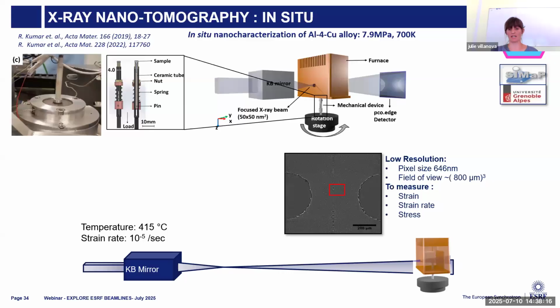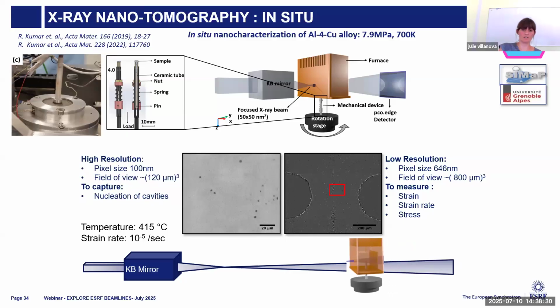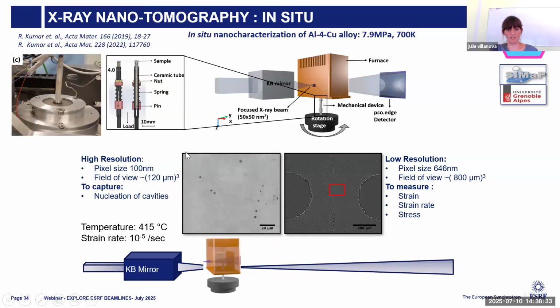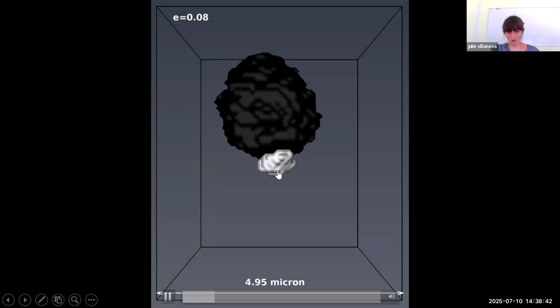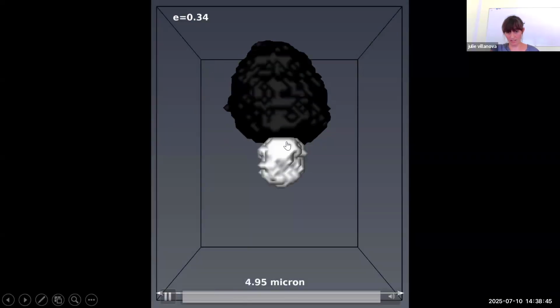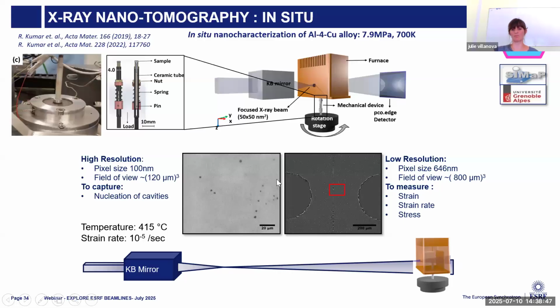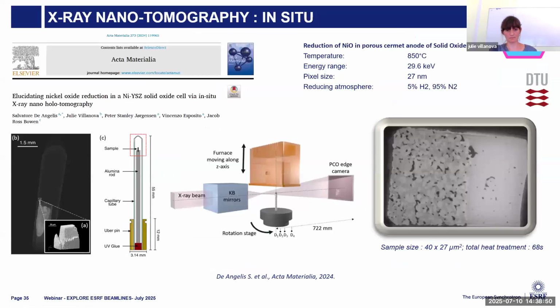And then we were performing a measurement at low resolution, looking at the notch and at the shape of the sample to determine the strain and the strain rate within the sample over time. And then by moving all the devices, performing high resolution to look at the microstructure, and especially here you see the metallic particles that we have in the matrix, but more especially looking at what we have in white here, the nucleation and growth of some cavities in the material.